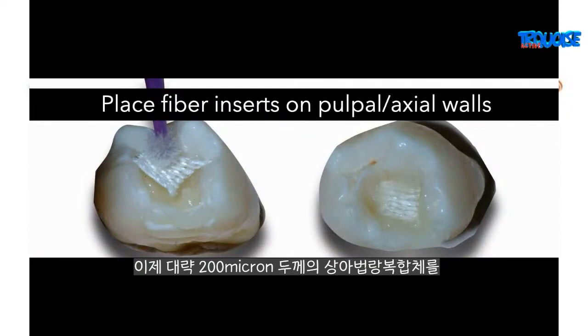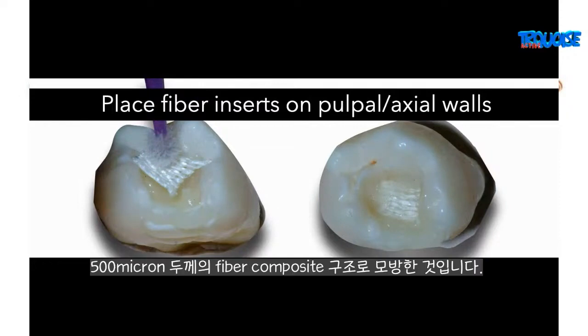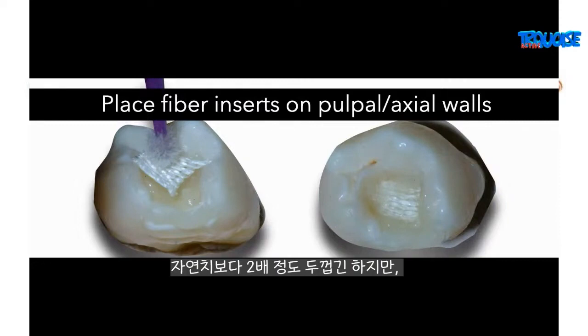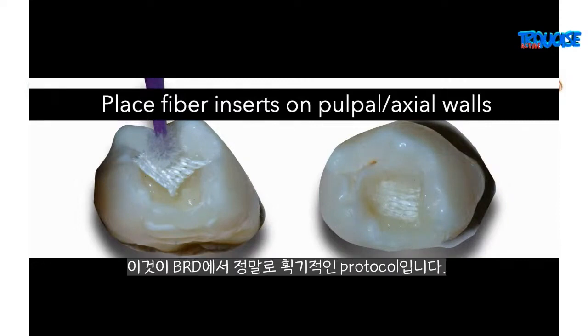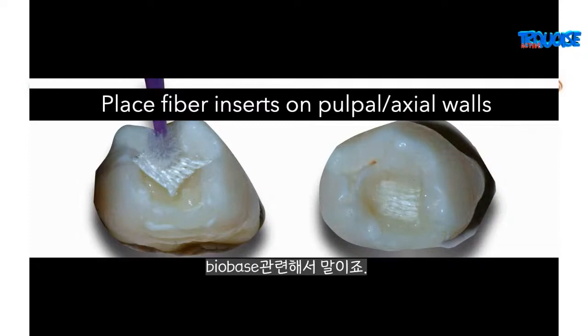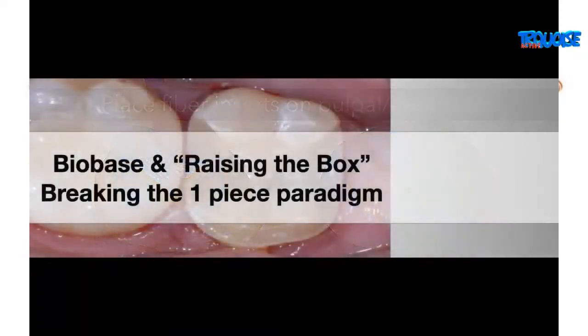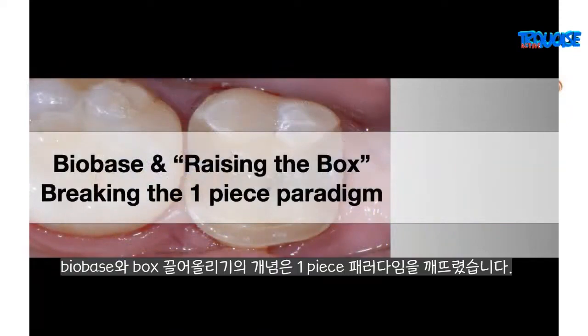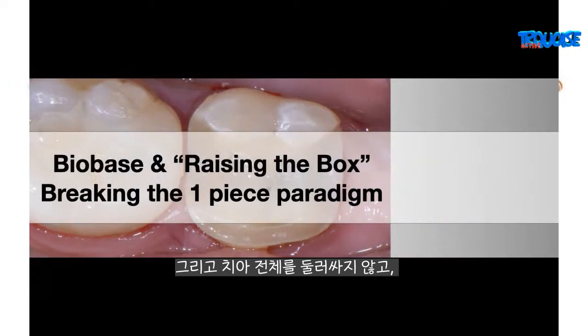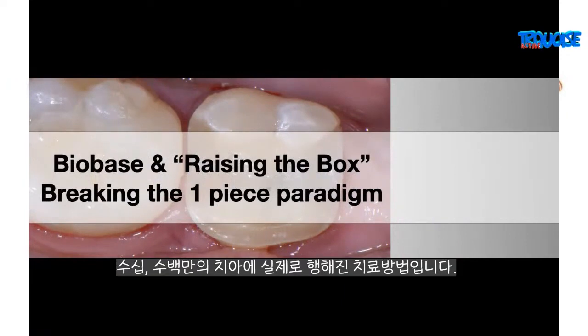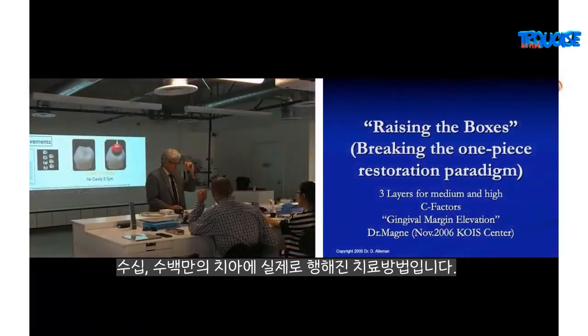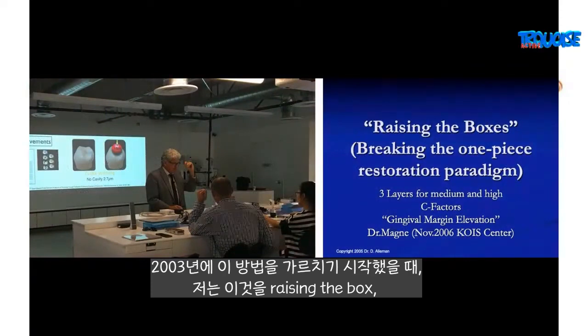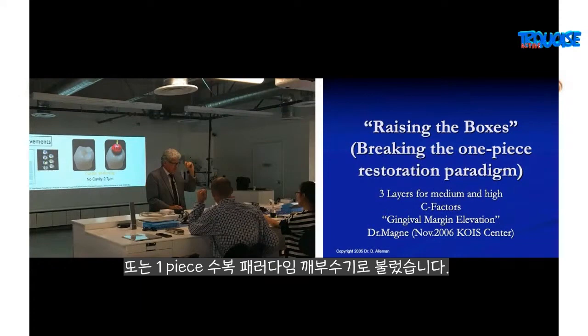So the dentin-enamel complex, which is about 200 microns thick, is now mimicked by a fiber composite construction that's about 500 microns thick. So it's about twice as thick as the normal DEJ, but this is the real breakthrough protocol in biomimetic dentistry for the BioBase. So BioBase and raising the box, this breaks the one-piece paradigm, and this is the real area where hundreds of thousands, actually million teeth have been restored without full coverage. When I started teaching this in 2003, I called it raising the box or breaking the one-piece restorative paradigm.